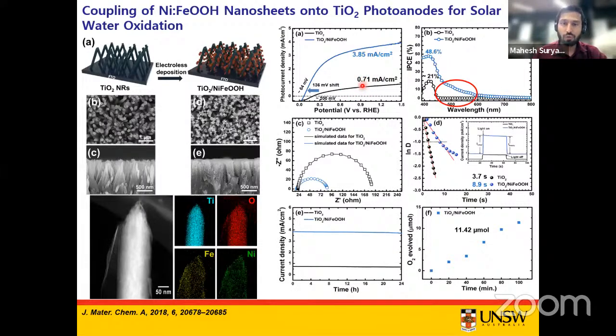Photoelectrochemical measurement again showed that there is a potential shift as well, and there is an improvement in the photocurrent density value. But interestingly, in this case, we have also observed that this NiFeOOH also contributes to the improvement in the visible light absorption capability of these TiO2 nanorod arrays, because the NiFeOOH shows a band gap of around 2.3 electron volts, and that's what we have observed from this IPCE. These are the basic EIS and lifetime analysis, which I'm not going to explain.